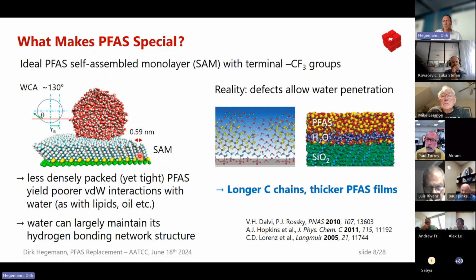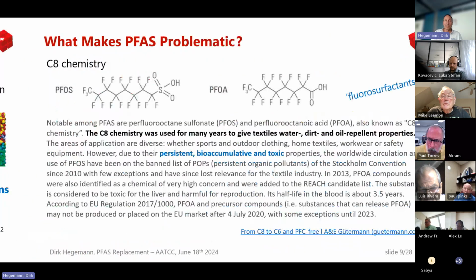The reality is a little bit different. If you want to do self-assembled monolayers, you always have defects where water can interact, since these are fluorosurfactants, so you need a reactive group to fix them on a surface, which is typically polar. Water can penetrate and even accumulate at the interface. For this reason, the effect is better when you have longer chains on one hand and thicker films of fluorocarbons. That is the reason why these micrometer-thick chemical coatings are typically used.